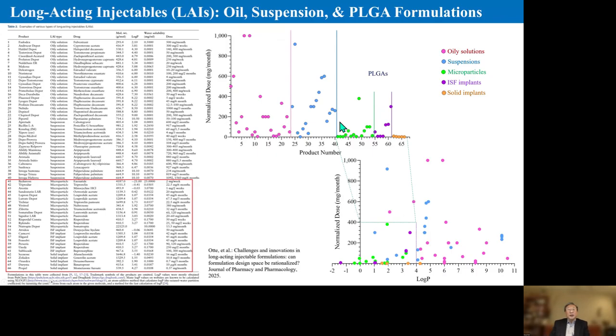So let me start with the currently available long-acting formulations. They start with the oily formulations and aqueous suspension formulations. They are usually for very hydrophobic drugs and delivering a large amount of monthly dose, up to 1,000 milligram or 1 gram per month. But PLGA-based formulations are rather small in size, and the maximum dose for monthly administration is less than 400 milligram, and it can deliver from very hydrophobic drugs to relatively hydrophilic drugs, because PLGA is the one to control the drug release kinetics.